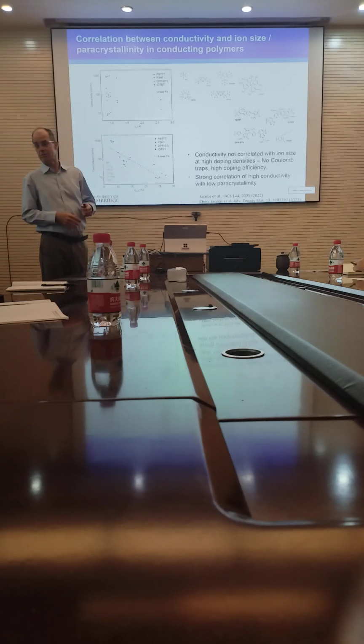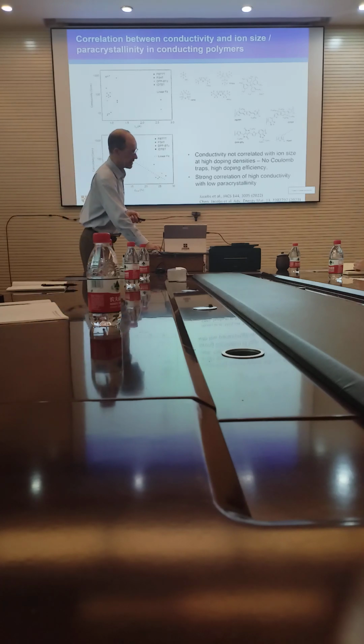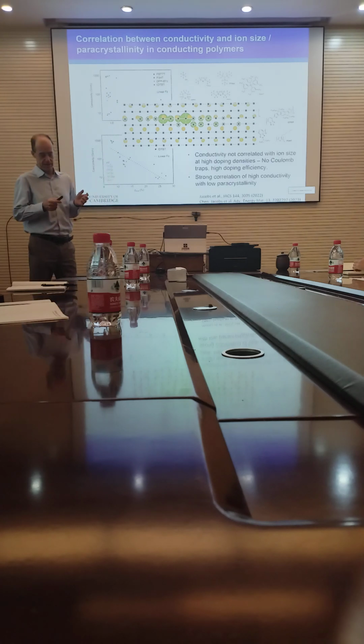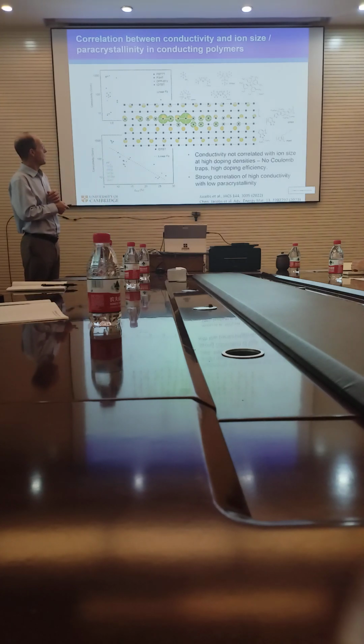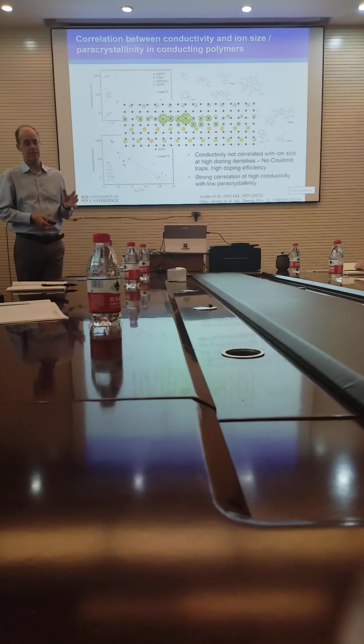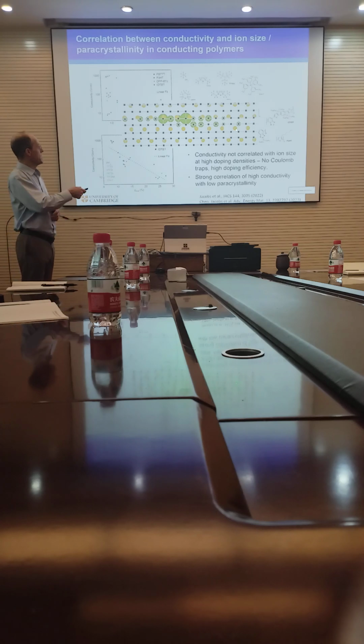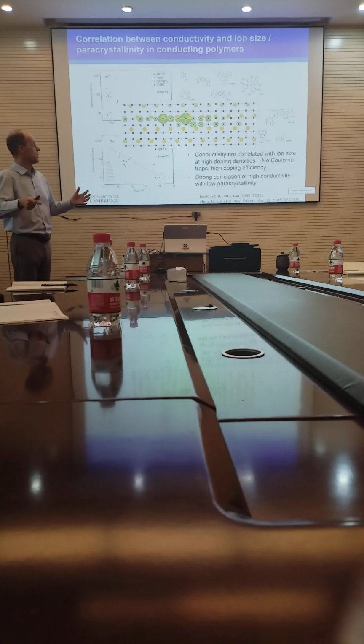So what's the reason why our expectation wasn't fulfilled? Why do we not see this strong dependence on ion size? The basic reason is shown here, a result from a simulation that shows the electron wave function in a system like this. The black dots here are the individual repeat units of the polymer. The orange dots are the counterions. And the green dots are essentially sites on which the electron wave function has a finite amplitude. What you see is that the electron wave function in these systems remains highly delocalized. It's more delocalized than the distance between the counterions, the orange dots.